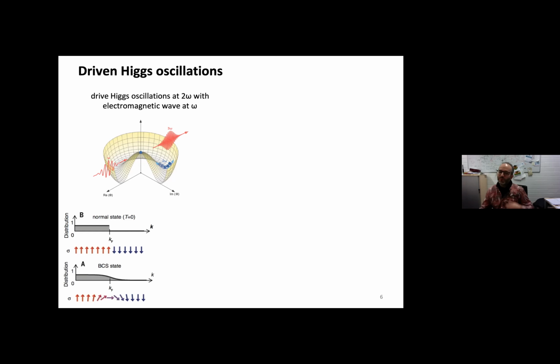So if we would think of a normal metal, and there we would now say every occupied state up to the Fermi energy, we would assign now with a pseudospin up. So a spin up is showing us an occupied state, a non-occupied state we would assign to a spin down. Then we have an effective spin 1/2 system, and the driving field could act as a pseudomagnetic field, and then we can use Bloch equations to calculate the response of our metal. This is something that is very well known.